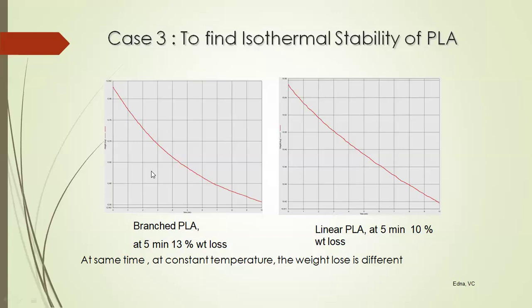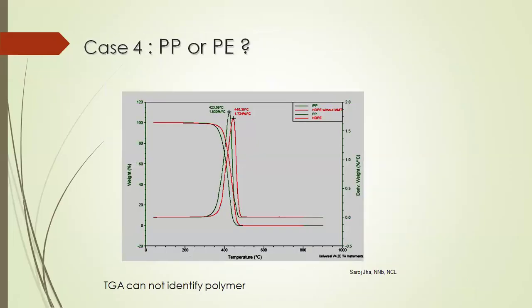So what you do, you do an isothermal TGA. That means heat your material at the processing temperature and hold it there with respect to time and find out how much weight loss is there at a particular time. Suppose a 4% or 5% weight loss is allowed for the processor. Then you can find out the processing time and you can safely tell the processor that yeah, up to 5 minutes you can process my polymer without a change in the properties. So you can use TGA as a tool to find out the processing times, not only weight loss and all.